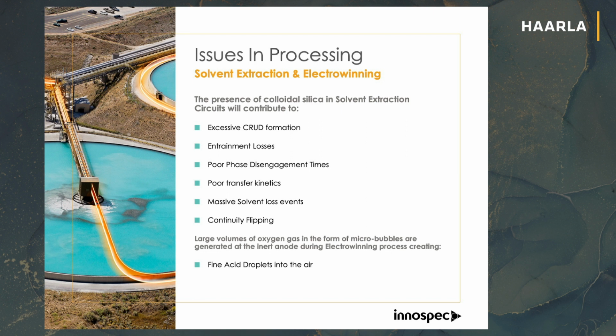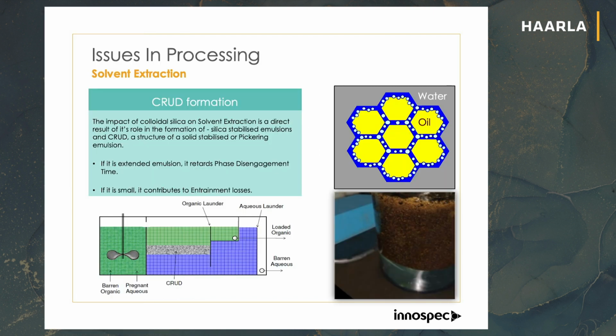I just want to move a little bit through these, taking the first one, crud formation. This is where having particulates in there is not helping you, because you form an emulsion between the aqueous and the organic phase, and that emulsion gives you this crud. The particulate matter stabilizes the emulsion, which is referred to as a Pickering emulsion. It's very difficult to break down. The bigger that crud phase is, the more copper you're using, and it has to go back through the recycling again.